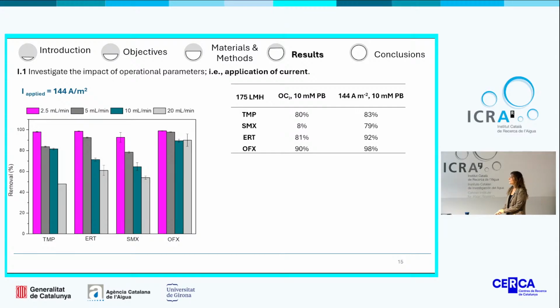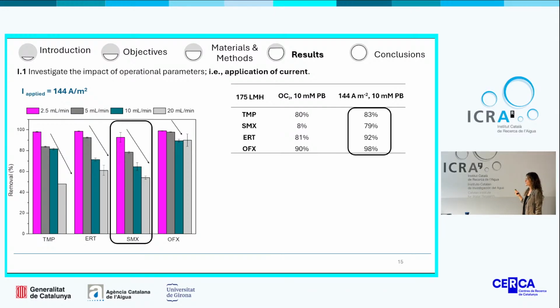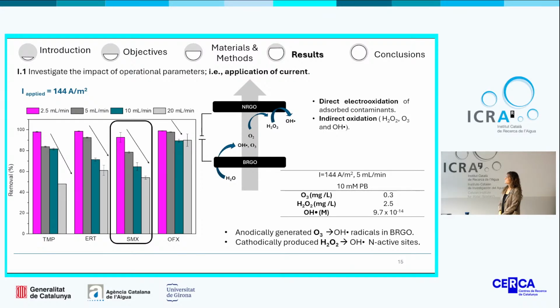When current was applied, we could observe a detrimental impact in all cases when we increase the flow rate. It's important to point out the case of sulfamethoxazole, which was previously poorly absorbed onto the sponge, and when the current was applied, especially at medium and lower flow rates, was almost completely eliminated. Well, the elimination of those contaminants, as I was explaining during the introduction, can be produced in two different ways: direct oxidation of the absorbed contaminant, which is really difficult to quantify in our scenario, and indirect oxidation through different oxidant species, which were quantified and we can see in this table.